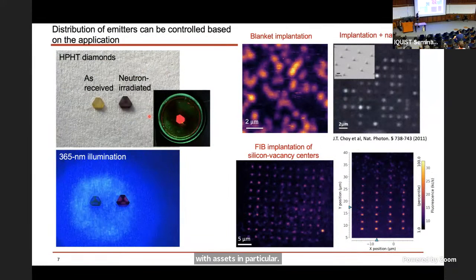So just some nice pictures showing what you can make, right? The nice thing about making color centers is that you actually get nice colors out of an implantation run if they're dense enough. What you see in this picture here are the high pressure, high temperature diamonds. The yellow one is the nitrogen-rich diamond. After we stick it inside a nuclear reactor and anneal it, it turns a little dark. But if you shine green irradiation on it and put a filter over it, you see this really nice red fluorescence. You can do the same thing with UV light.